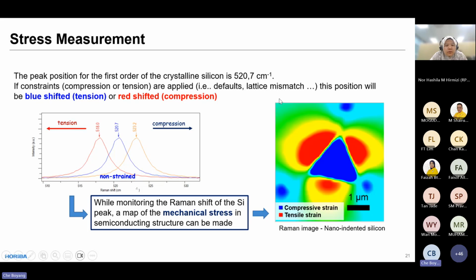So here we map this piece of silicon, and we can find out in the middle triangle region, those peaks are more shifted to the right-hand side. So we know they are under compression. And in these red color regions, the peaks are more shifted to the left-hand side, so they are under tension. So by doing the Raman mapping, we can get the local mechanical condition of this silicon material, and it may be related to the failure analysis of this kind of device.